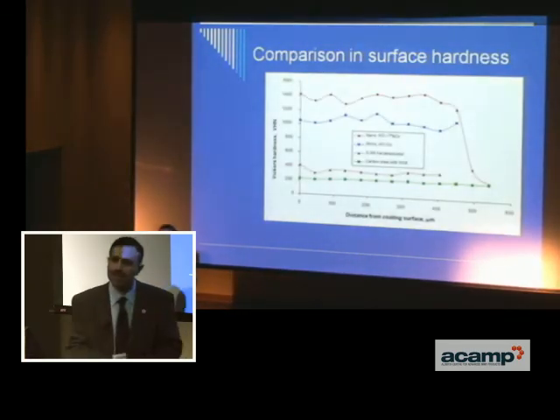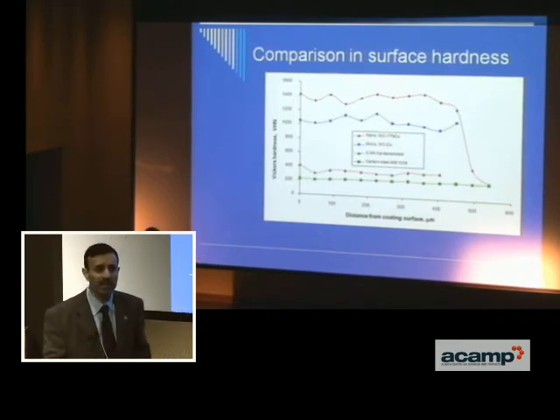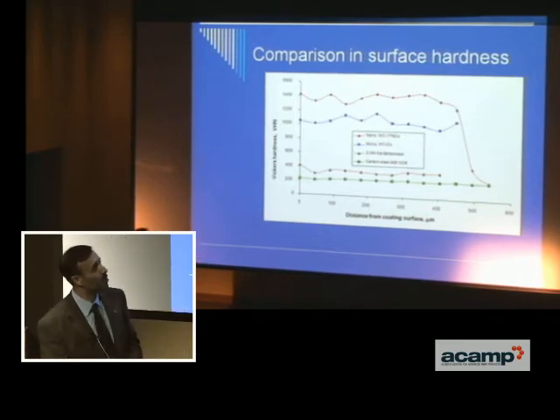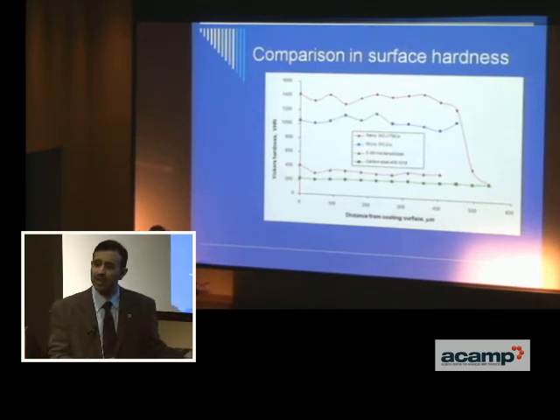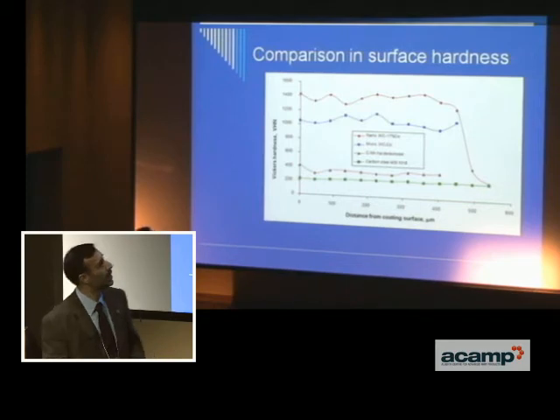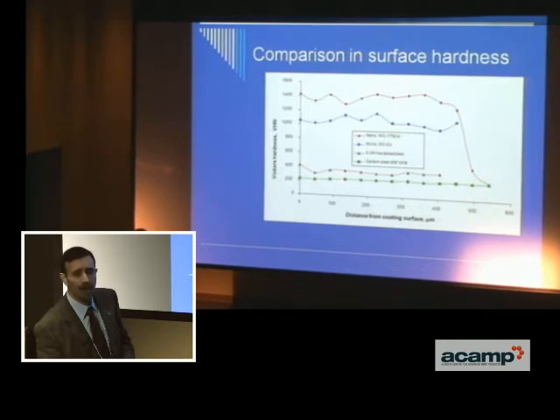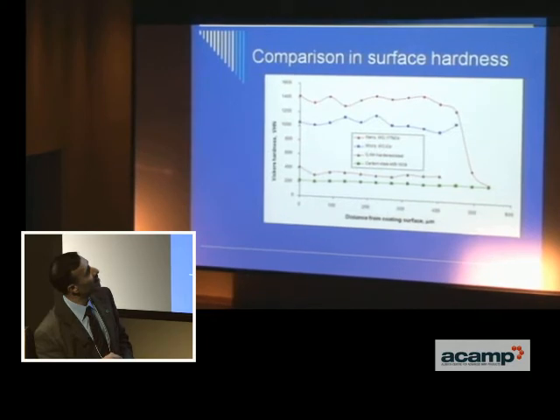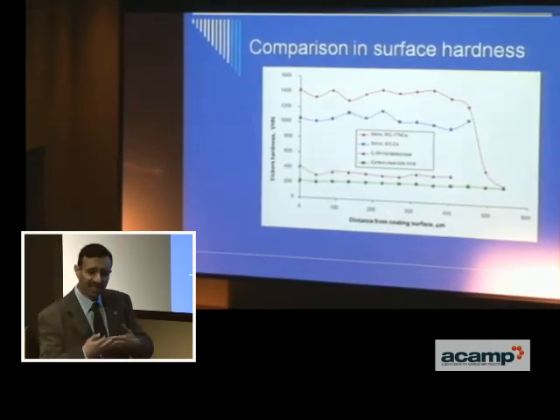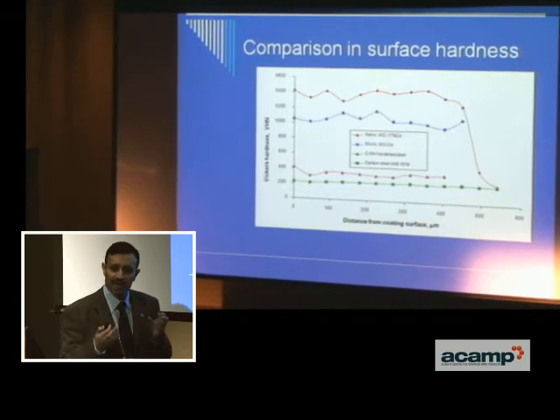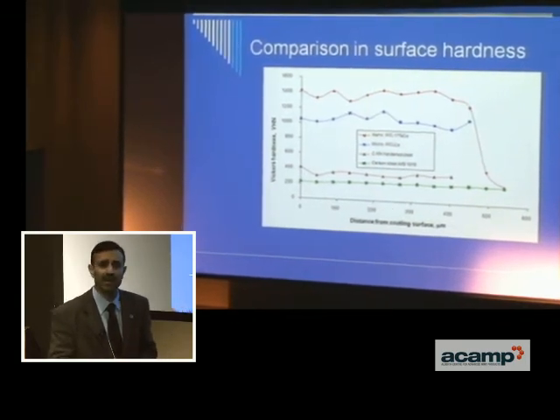So we want to look at the mechanical properties, and we can do that from a number of tests. Normally when we're talking about wear resistance, we try to correlate that with coating hardness. If we compare the untreated steels used in this industry, a carbon manganese steel, we get hardnesses down here. This is untreated. This is the treated hardened steel, which has been tempered as well, so it has some toughness. This is the microstructured coating, and then we have the nanostructured coating up here. So there is this difference in hardness. We've managed to maintain some of those properties that we want from the nanostructured powder.